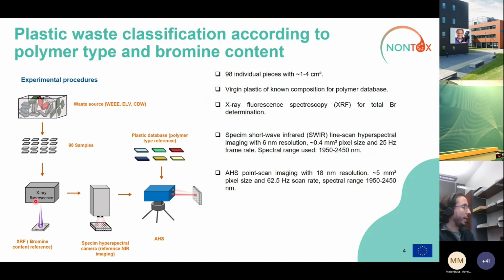And then we analyzed them with a reference X-ray fluorescence sensor, which gives our reference for bromine content, and also with a reference hyperspectral camera in the lab, which is a commercial system that works as a reference for the hyperspectral images we get. So from this side, we can get a reference for bromine concentration, and from here, we also used a plastic database, so virgin plastics with known polymer compositions to serve as a reference for our classification of polymer type.